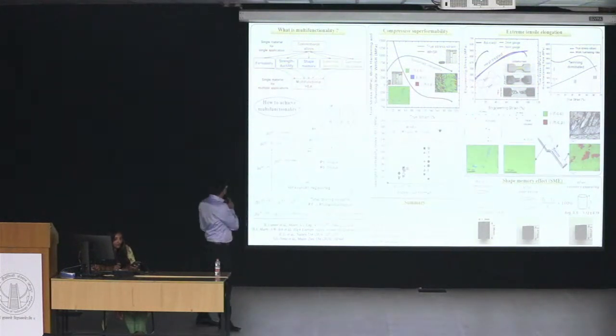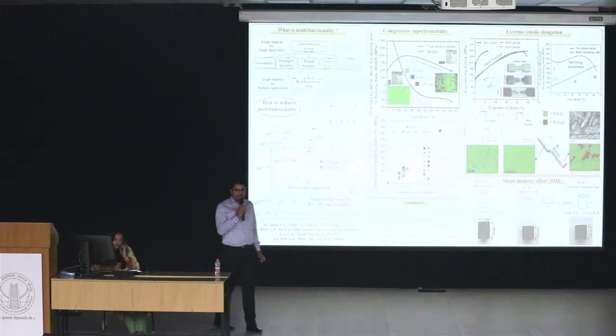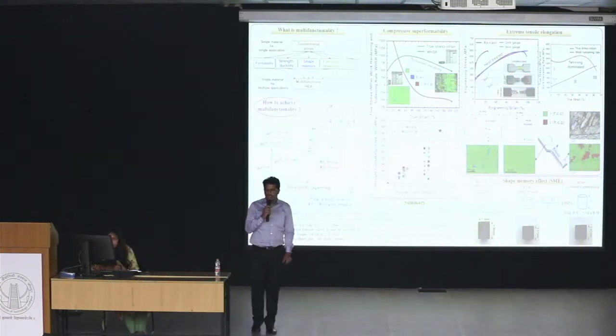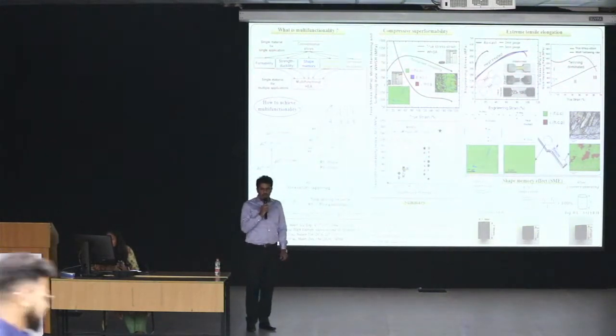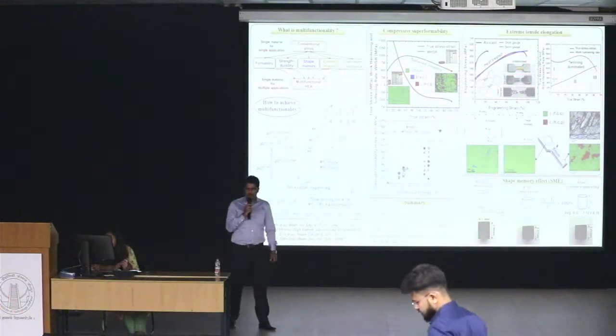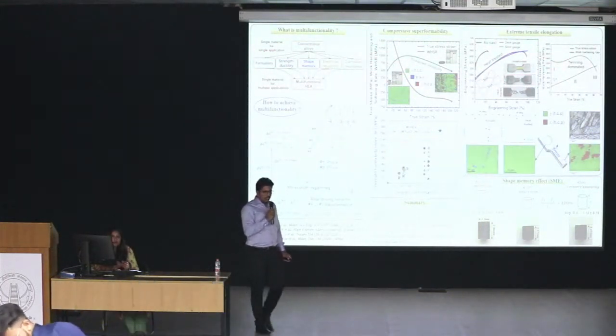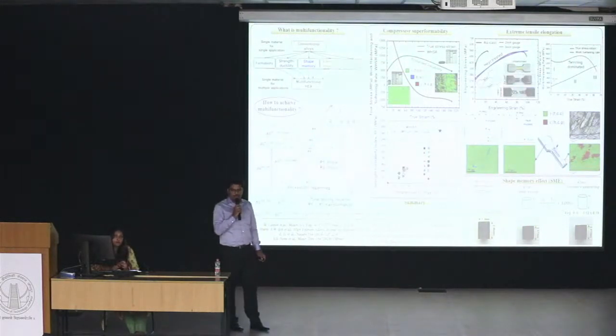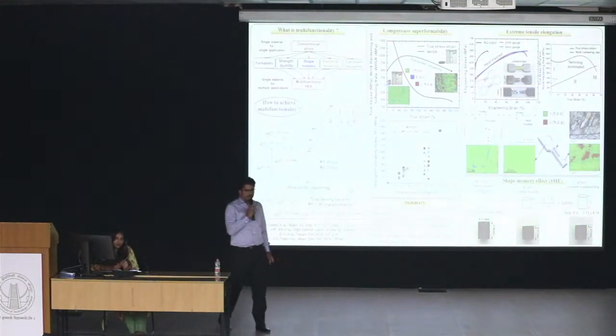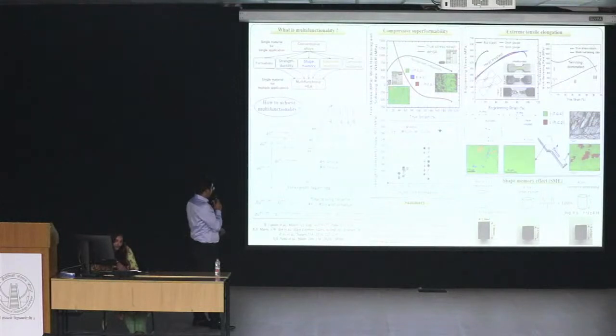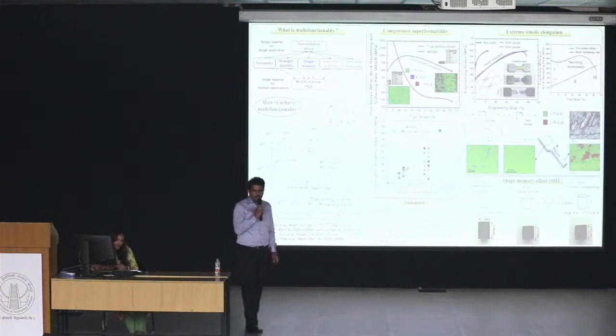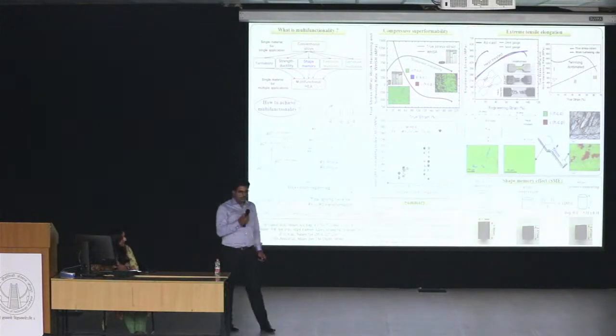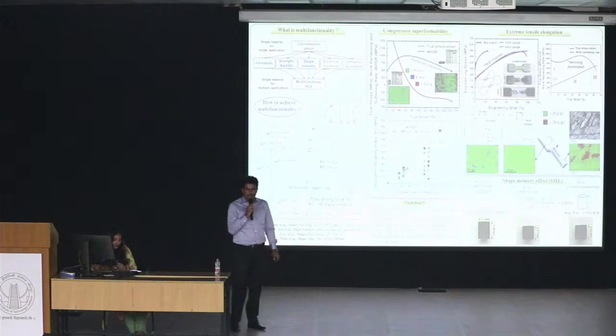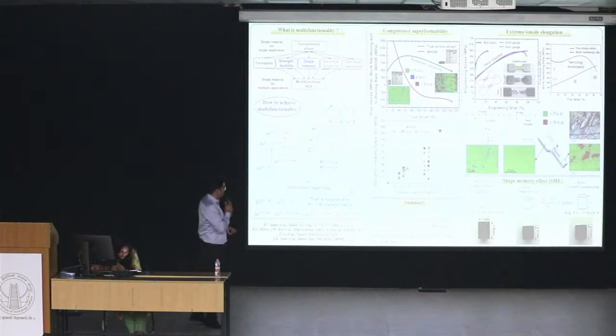Now, if we see two important terms that have been coined back in 2016 and 2020, that is metastability engineering and microstructural flexibility. According to those concepts, the phase stability in high entropy alloys can be made sensitive to the alloy chemistry, by virtue of which the gamma phase stability can be manipulated in such a way that multiple deformation modes such as transformation induced plasticity and twinning induced plasticity can be activated during plastic straining. The gamma phase will transform into epsilon phase, which will increase the work hardenability of the material at the end and provide excellent mechanical properties. And the microstructural flexibility concept gives rise to another term, that is reverse martensitic transformation, which is the exact concept for the shape memory effect that is observed in this material.